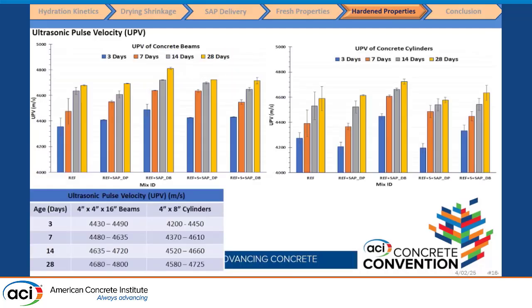Further, we also tested ultrasonic pulse velocity. For the pulse velocity, we tested using beams and cylinders. We found that the direct addition of SAP had a marginal increase at 3, 7, and 28 days, but we also found a similar increase using the dissolvable bag, which is DB.